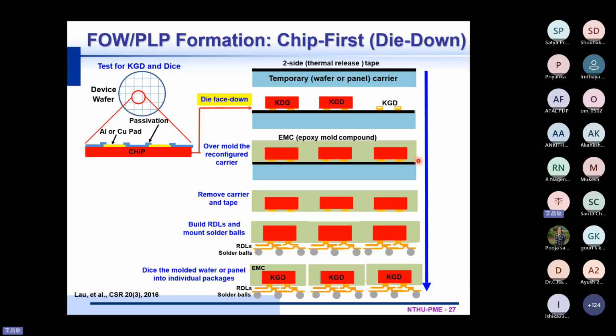So next, I will show you, if we do not use the thermal release tape, another option is to use the die attach film. But this process needs additional cost and steps here. Okay, and during the process, with the wafer carrier and the panel carrier, because of CTE mismatch, the wafer will have warpage. The panel carrier warps more than the wafer because of the size issue. The warpage is not good.